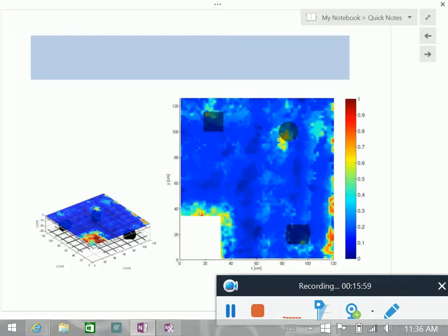Remember, in non-destructive evaluation, you are looking for a parameter which somewhat relates to the type of damage you are looking at. In this case, the frequency wasn't a good feature. We sometimes call that a feature. But the width, the half power bandwidth, was.